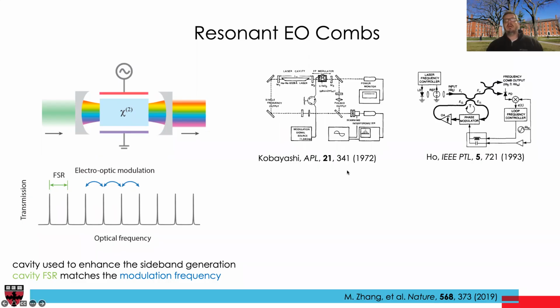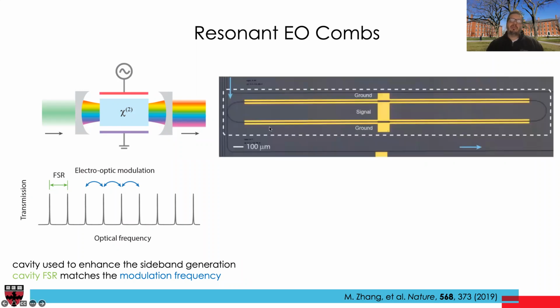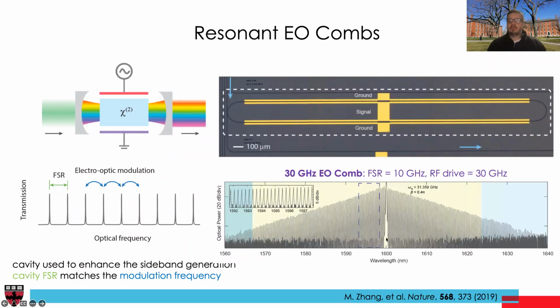before several times, using discrete component lithium niobate or lithium tantalate, in this case a lithium niobate modulator. And in our approach, we took our chip-scale ring resonator, similar to the one I showed you at the beginning, put electrodes on it, essentially a phase modulator combined with it, and then coupled it with an optical waveguide. And by driving these electrodes with about 10, 20, 30 gigahertz RF fields, we could generate a broad comb spectrum as shown here. So this comb was pumped at about this wavelength here, about 1600, and we applied an RF signal, and we were able to get this nice broad comb.